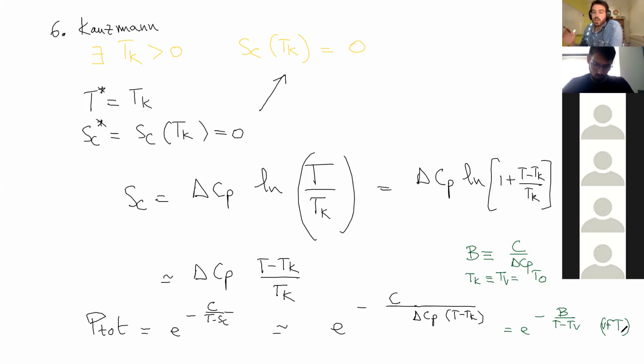It's the VFT law again, and so the time for relaxation is the inverse of that probability in an ergodic description, and so you recover the empirical behavior. So you see, we have a temperature that describes the empirical fitting of the viscosity. We have a temperature that describes the phenomenology of free volume, at which point the free volume vanishes, and we have a third temperature proposed by Kauzmann at which the configurational entropy vanishes, which is related to free volume.